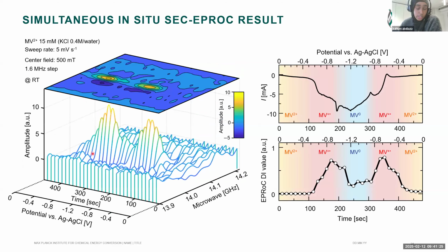But he can also do a simultaneous in situ spectroelectrochemical EPR, where instead of applying a potential and measuring, he just scans the cyclic voltammogram and measures at the same time. So both electrochemistry and EPR are happening at the same time. And so with this, you can monitor any changes that are occurring as a function of potential.